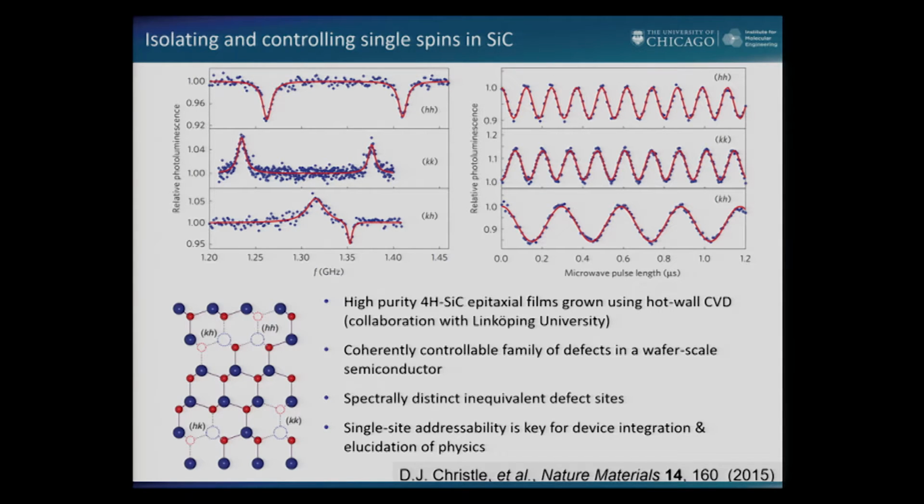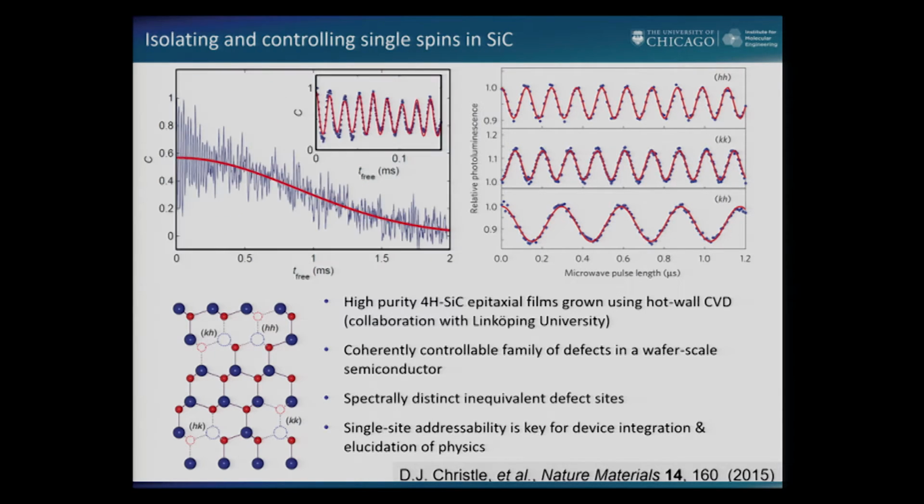So what's quite extraordinary in this data is by tuning your spectrometer to the right frequency, you can identify the single spin in the lattice, know where it's pointing, measure its frequency, and find that surprisingly in these systems, which are just, in often cases, commercial materials, the coherence times are surprisingly long. They're a few milliseconds. And the reason this is surprising is that there are lots of nuclear spins in these materials, roughly 5% isotopes spread throughout the material. Nothing has been purified here, just standard wafers. And it made us wonder why the times could be so long when the material is so crappy.